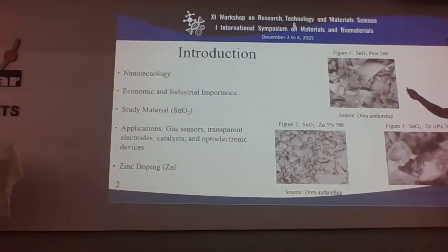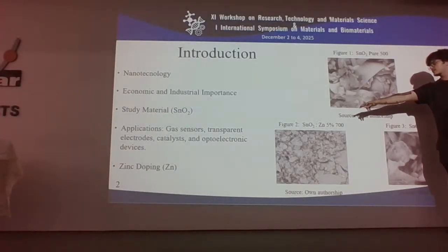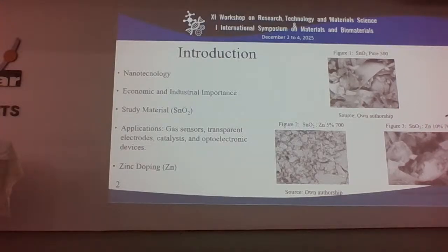The material studied in this work is tin oxide, SnO2, and it is not a random choice. It was because of tin oxide's semiconductor properties and its thermal and electrical stability. SnO2 is a widely studied and widely disseminated material, and its principal applications are in gas sensors, transparent electrodes, catalysts, and optoelectronic devices. Doping is used to improve some property of the material. Since I use zinc, the property I want to improve is the electrical one. These are some figures of my SEM samples, just to exemplify what the nanoparticle looks like: here the tin oxide, tin oxide with zinc 5%, and here tin oxide with zinc 10%.